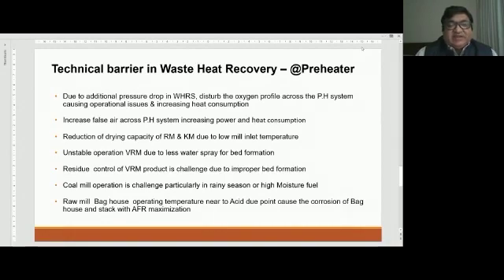As we discussed, whenever you increase the oxygen profile, your false air goes up, which sometimes has a negative impact on the process. Whenever the plants have limitations, the preheater fans suffer because sometimes they cannot maintain the oxygen level, as India is also using quite a significant amount of pet coke with high sulfur, which needs a little more oxygen in the process requirement to produce the clinker.